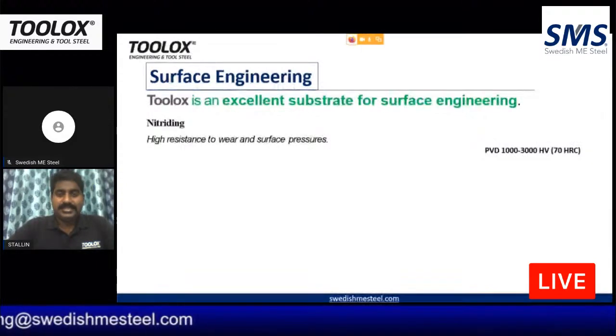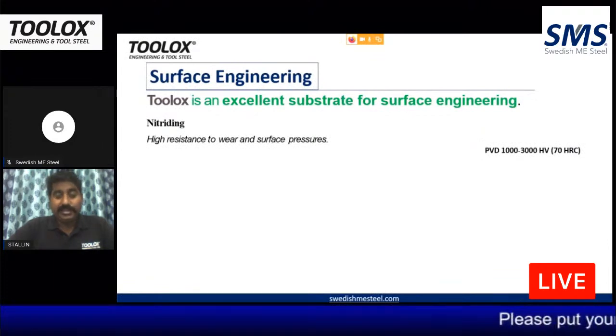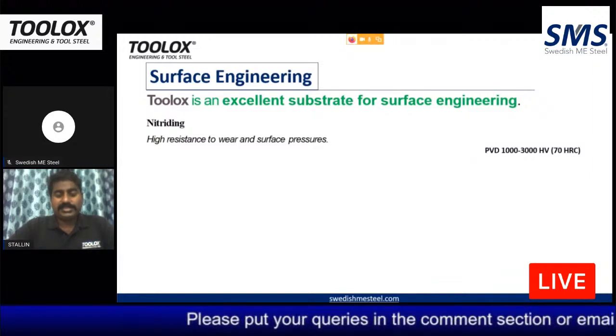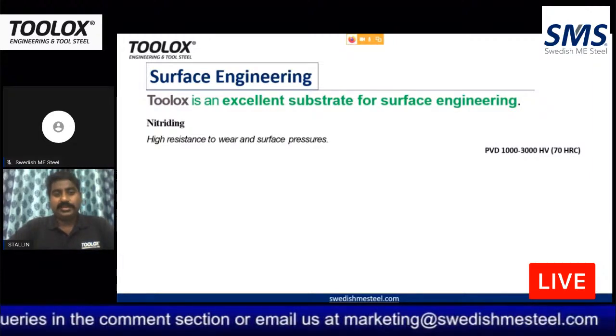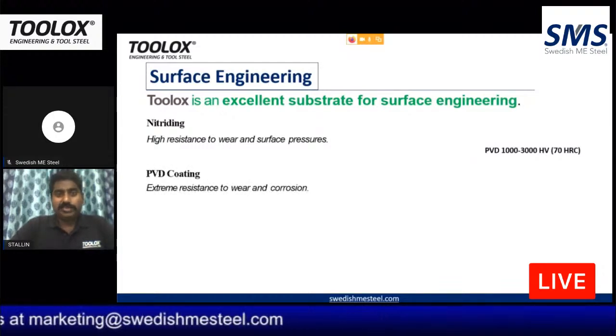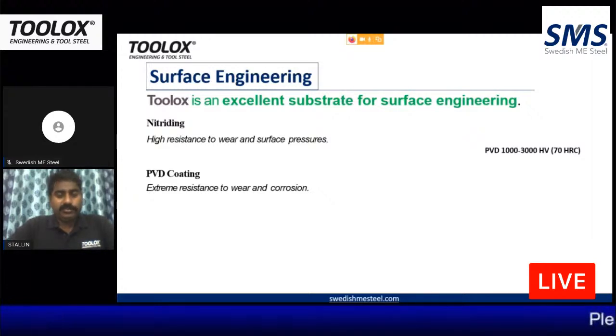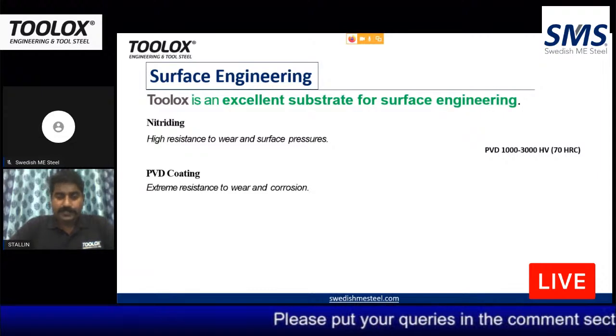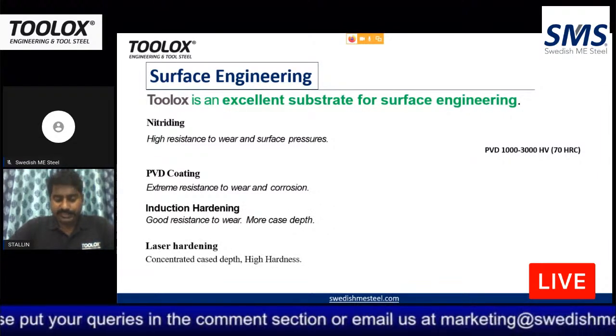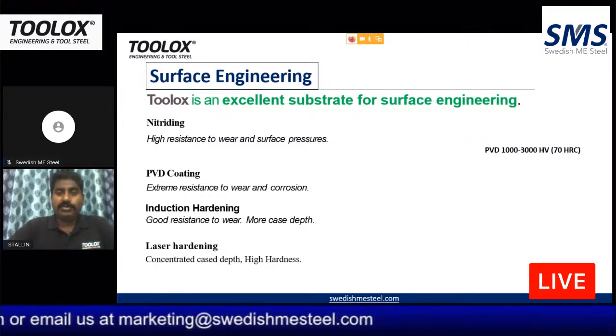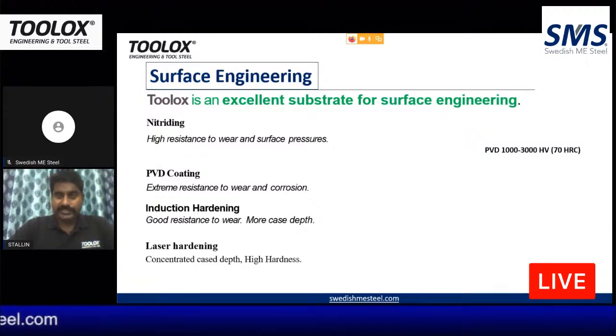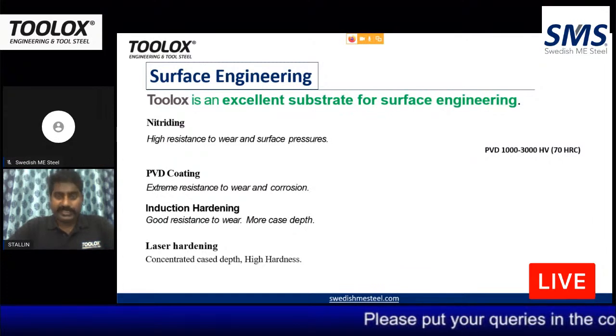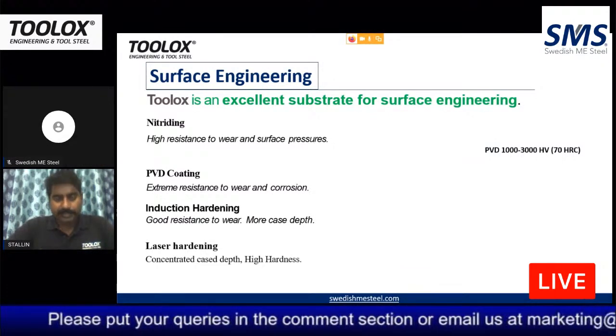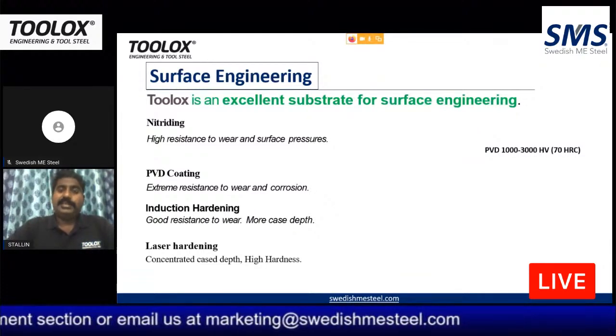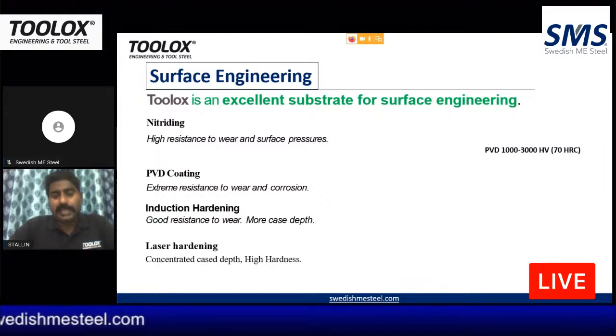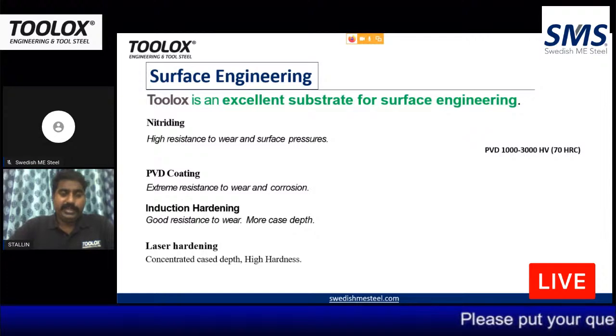Toolox is an excellent engineering substrate for any of the surface engineering things that you do. All these surface treatment processes like nitriding provide you high resistance to wear and surface pressures. PVD coating is also extremely good in providing good resistance to wear and corrosion. Induction hardening also gives good wear resistance, and it is an important option where, if you want the case depth to be more than the normal surface treatment process, you can always opt for induction hardening. And laser hardening is an upcoming, very exciting surface treatment process where the treatment is very localized, and you can increase the hardness only in the area which you really want.